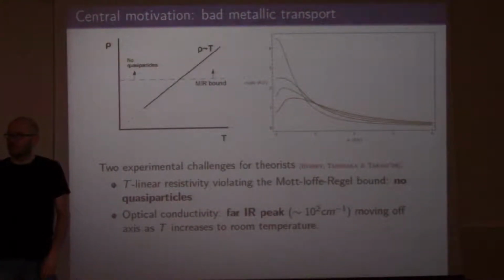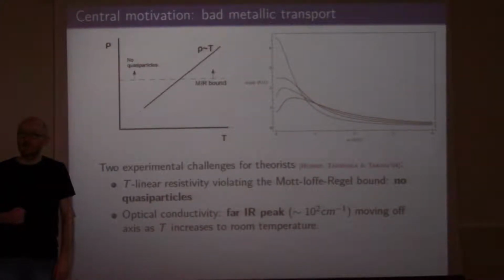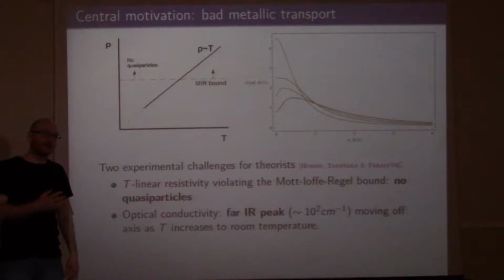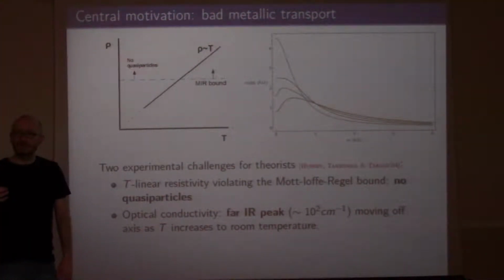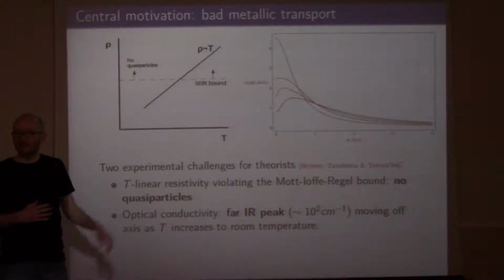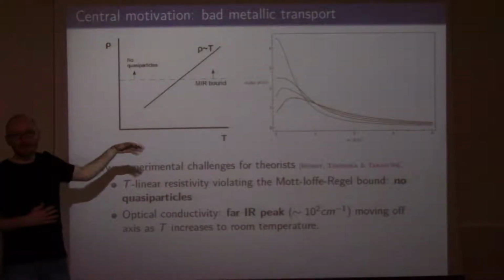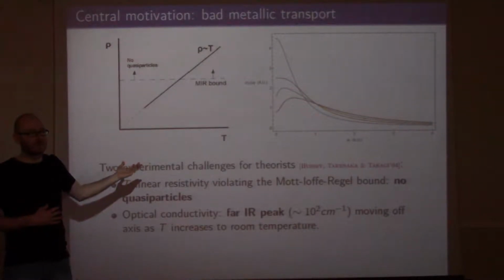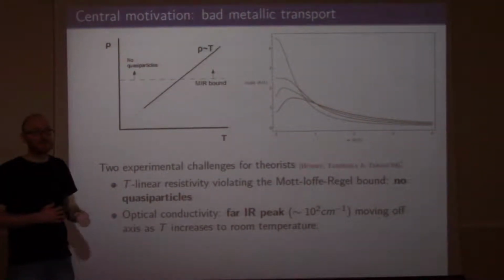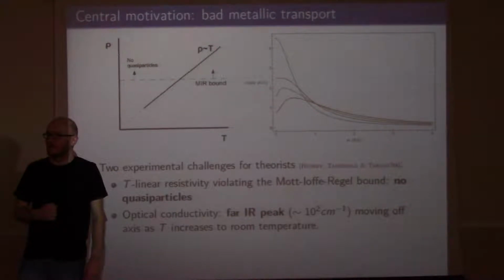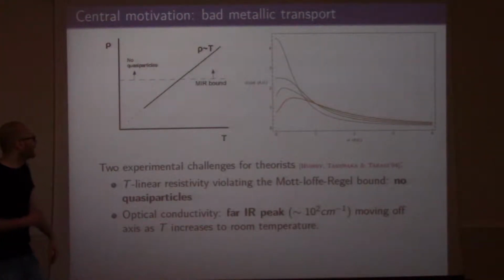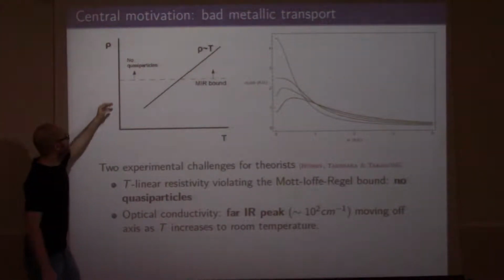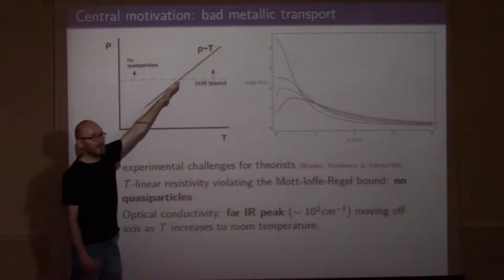So that's the first problem, because for a conventional weakly coupled metal, Landau-Fermi liquid theory tells you that the resistivity should go like T squared. So the fact that the resistivity goes linear in T is already presenting a challenge, because there's no consensus on the mechanism that produces this linear in T dependence. There's a second problem, which is that the resistivity grows without bound.